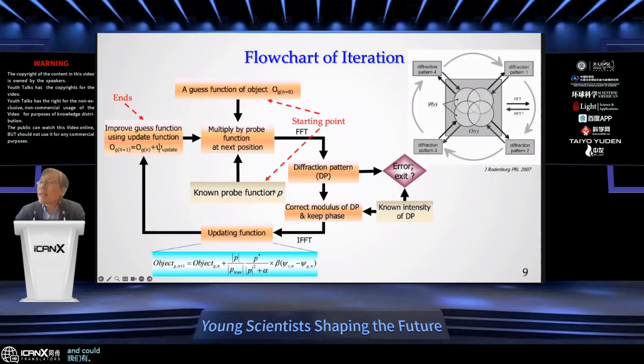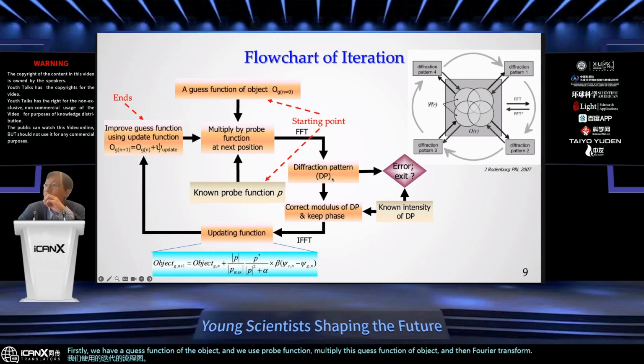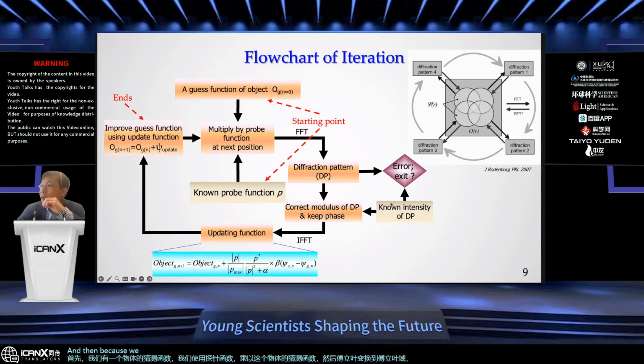And this is the simplest flowchart of the iteration that we use. Firstly, we have a guess function of the object, and we multiply the probe function by this guess function of the object, and then Fourier transform to the Fourier domain, which is the diffraction pattern. And then because we acquire the intensity of the diffraction pattern, we can replace the modulus of the calculated diffraction pattern and keep the phase. And then we inverse Fourier transform to update the object function at this probe position. And then we can continue to the next probe position, and so on and so forth.